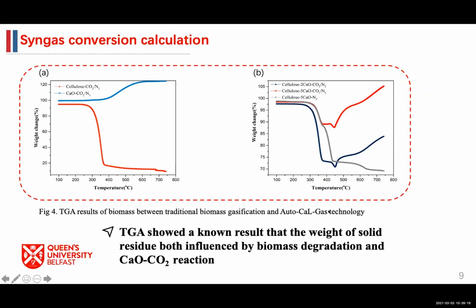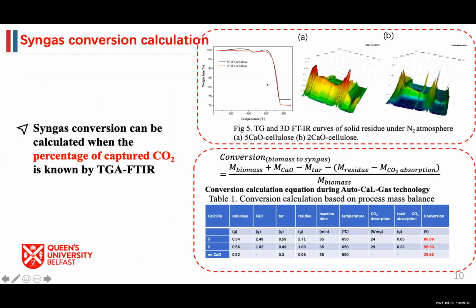So in order to calculate the conversion from biomass to syngas, the TGA showed that the weight of solid residue is influenced by both biomass degradation and calcium oxide carbonation, which makes it difficult to calculate the conversion because we can't simply compare the weight of solid residue before and after gasification. So in order to solve this, I collected the solid residue and did TGA in a nitrogen atmosphere, and we know the percentage of CO2 desorption, and the released gaseous component was detected by FTIR and confirmed to be CO2. And based on the provided equation, we can calculate the conversion, and we achieved a significant conversion enhancement from around 30% to 86%.